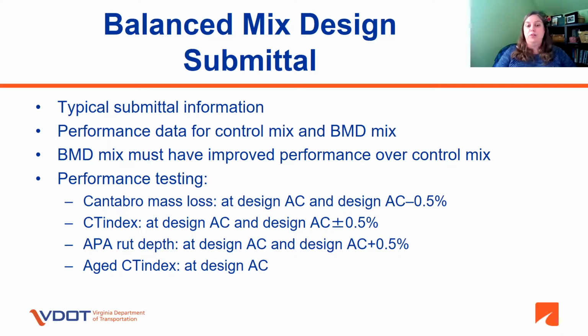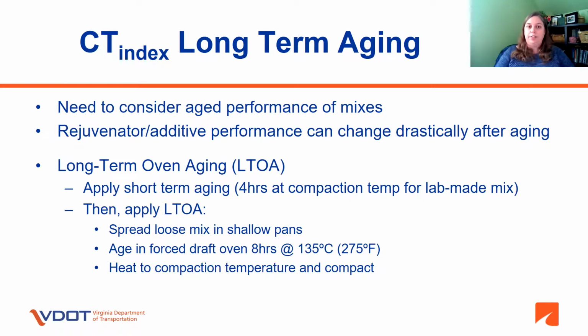As you're designing, you may want to keep in mind that you want to have a little bit of cushion built in your design for production variation. In addition to these, the aged CT index must be submitted at the design asphalt content. The aged CT index gives us an idea of what the long-term performance of the mix should be. It also allows us to evaluate rejuvenators or additive performance over time.